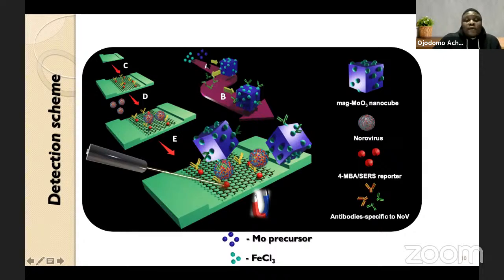And via the hydrothermal synthesis and also the oxidative reduction of the molybdenum precursor, which we optimized and controlled, with different temperatures and different ramp times of the hydrothermal treatment, we finally achieved the whole cubic nanostructure. So the whole process comes from the synthesis, then antibody labeling, which is the norovirus antibody that is specific to the norovirus.